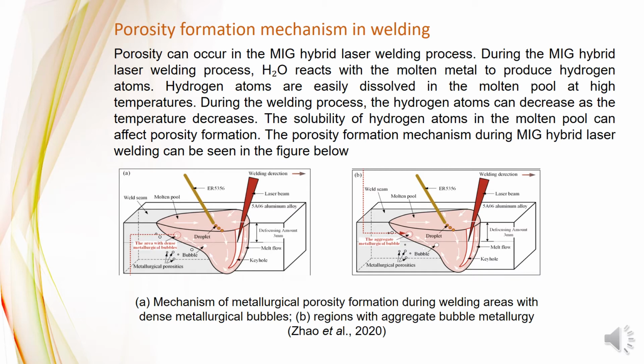During the heating process in MIG hybrid laser welding, the molten pool area contains a solution of hydrogen atoms. The dissolved hydrogen atoms form bubbles. The movement of hydrogen atoms is influenced by the flow behavior of the liquid metal. The cooling process causes the solubility of hydrogen to be reduced, and the hydrogen bubble cannot escape from the molten pool of melt, causing porosity. The shape of the porosity is irregular and has a large size.